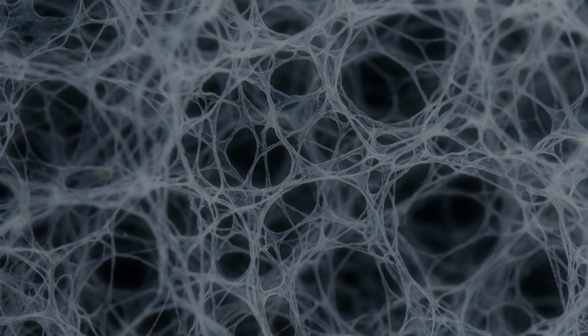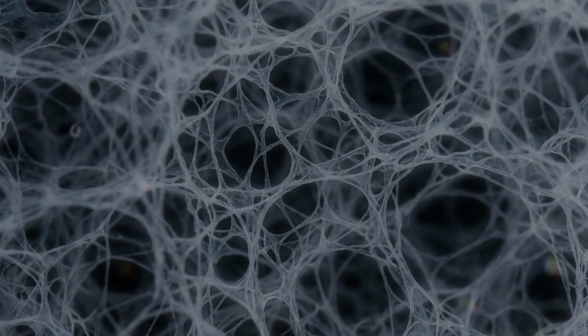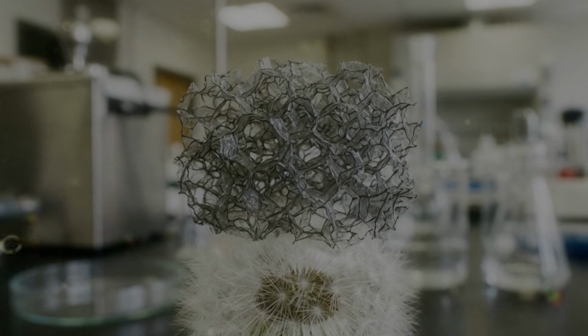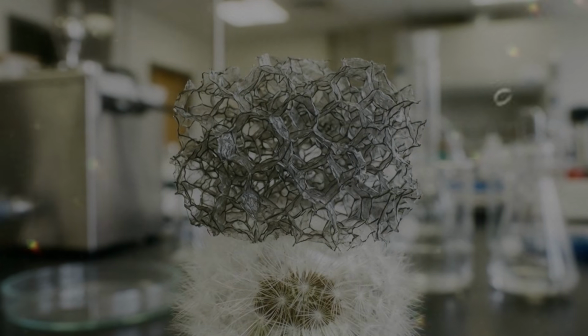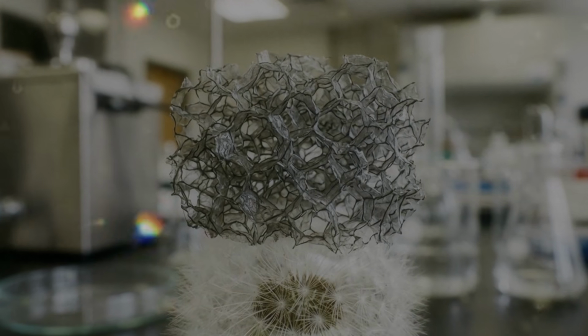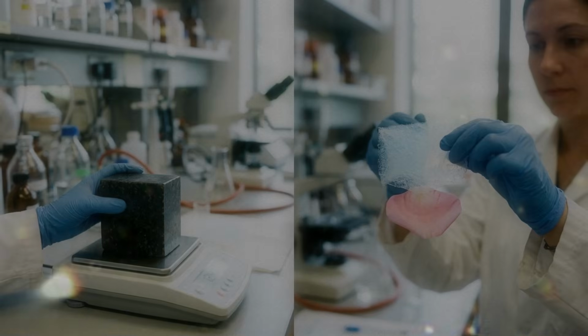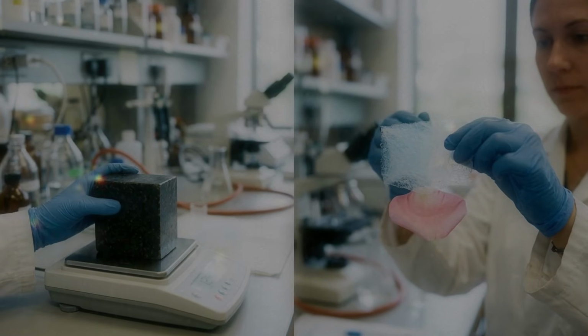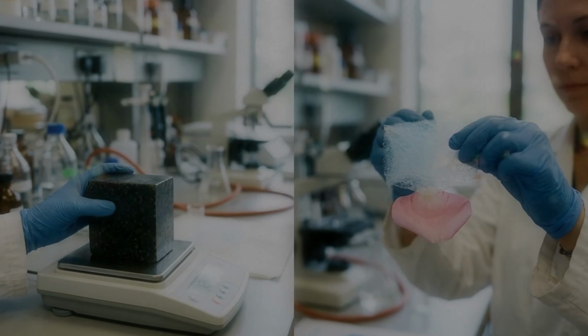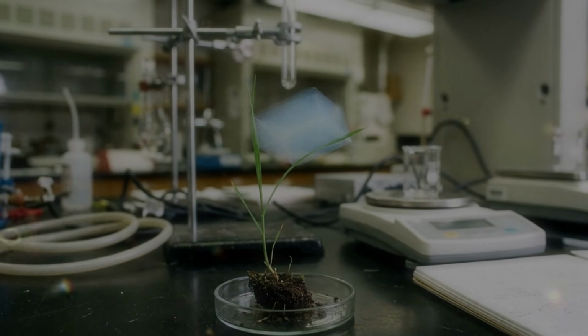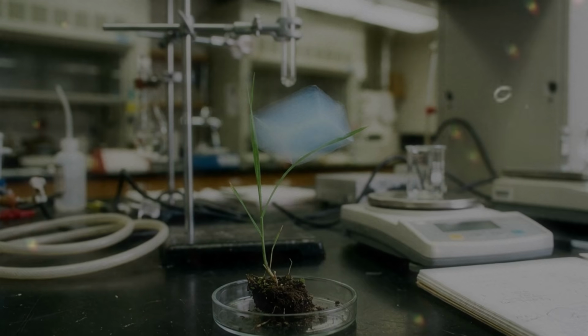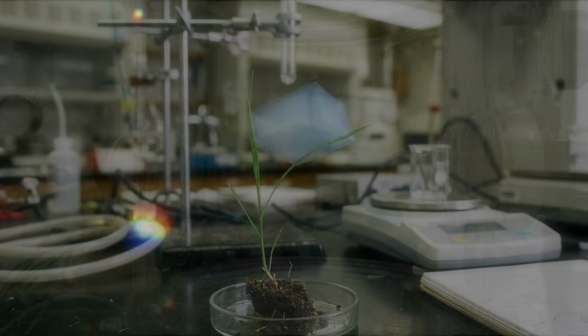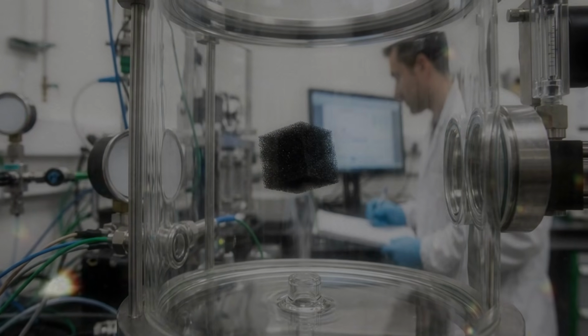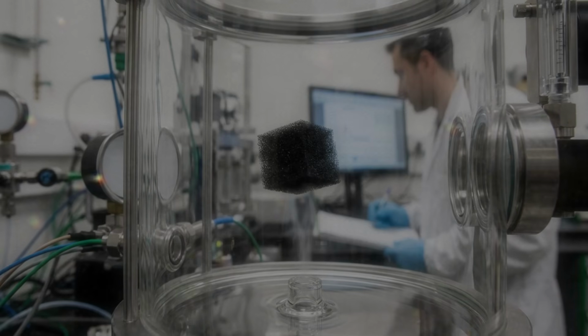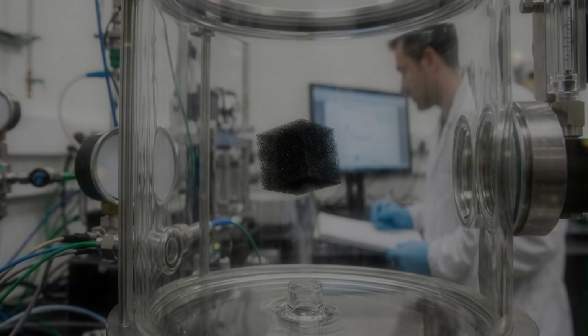The aerogel must also connect to ordinary solid components. Attaching a wire to a delicate carbon sponge is not as simple as attaching one to a metal plate. A rigid contact may tear the aerogel when the device bends. An adhesive may fill the pores and block useful surfaces. A coating may increase strength, but also reduce sensitivity. These practical details rarely appear in photographs of a sample balanced on a flower. They become important as soon as the material leaves the research bench.